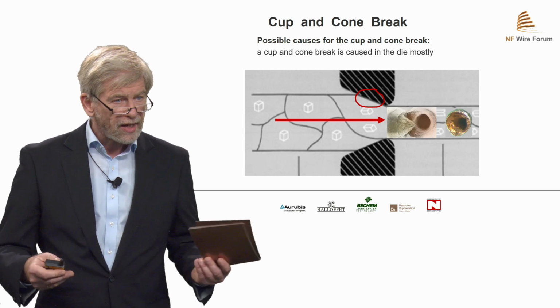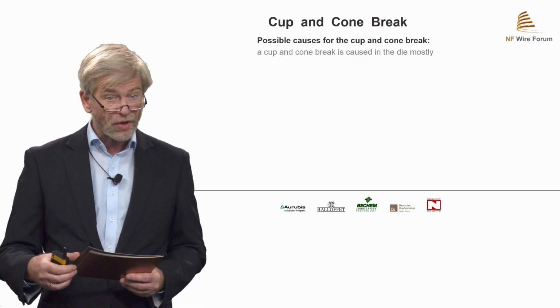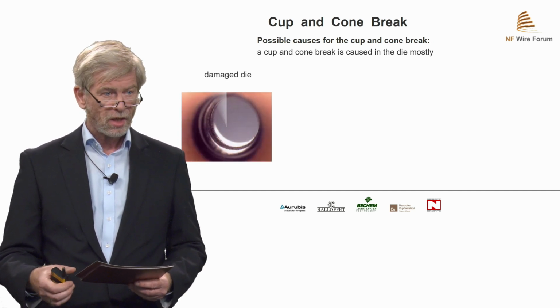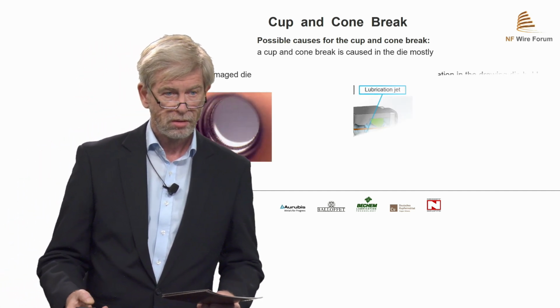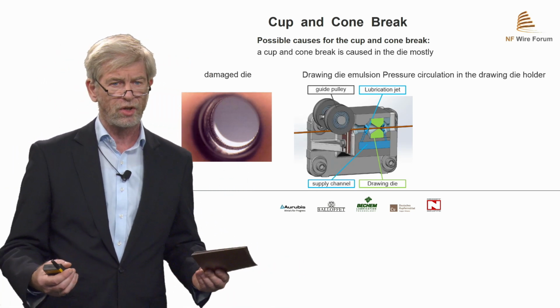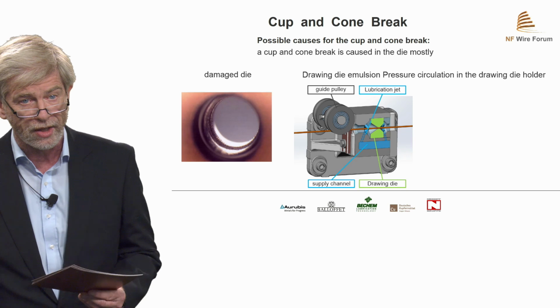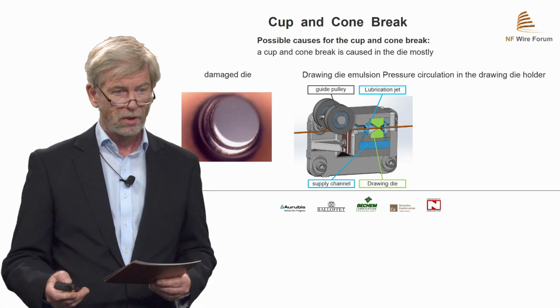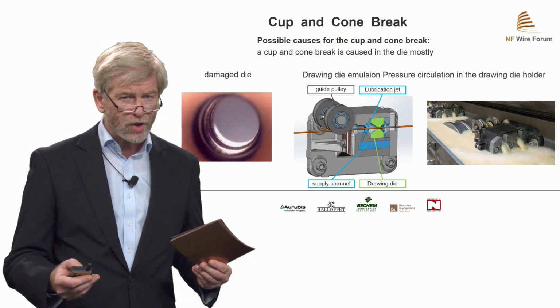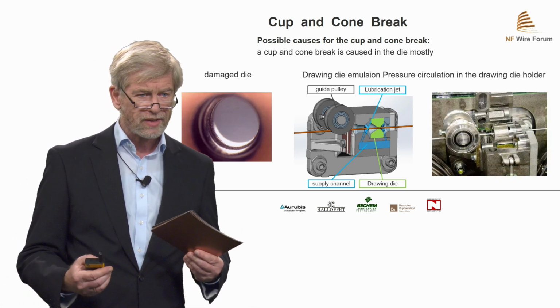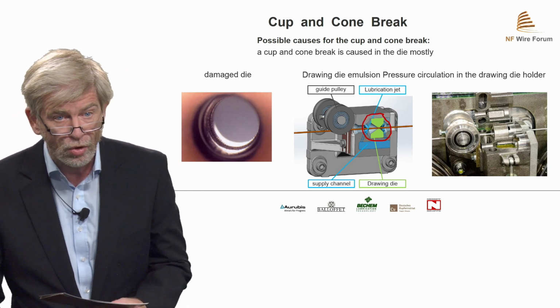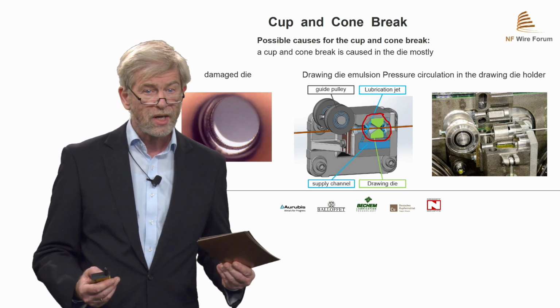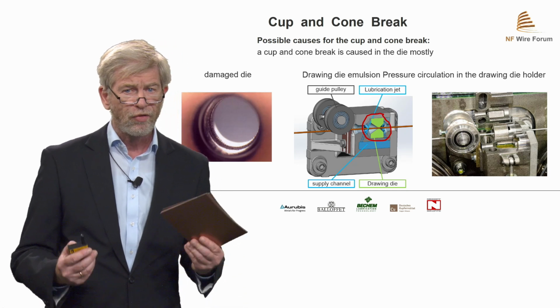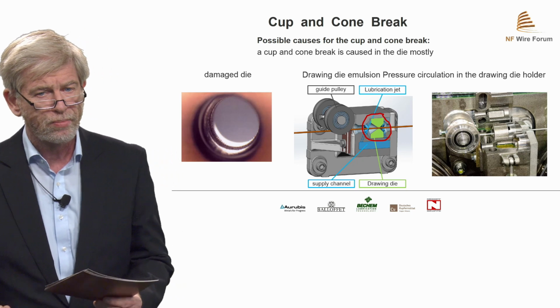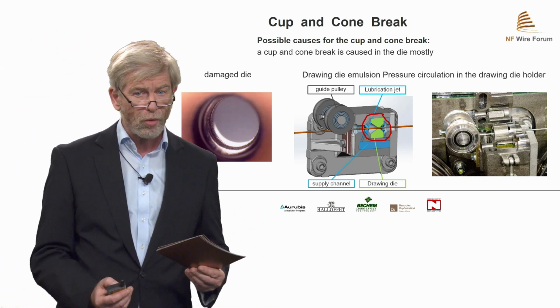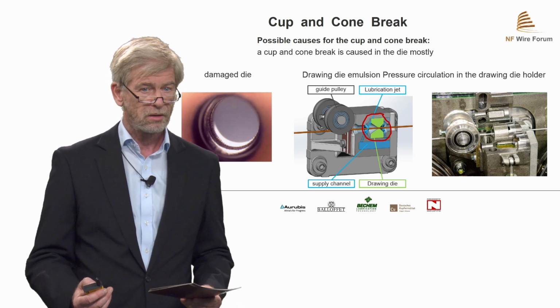Possible cases for a wire break: a cup and cone break normally is caused in the die. Here we see a damaged die. The next picture shows an emulsion circulation system in the drawing die holder, how it should be. Emulsion flow, how it should be. But if the die holder is dry, then it's creating problems. If you don't clean the lubrication system regularly, the flow channel can become clogged with deposit or with copper flakes. No lubrication comes to the die, a wire break is inevitable.